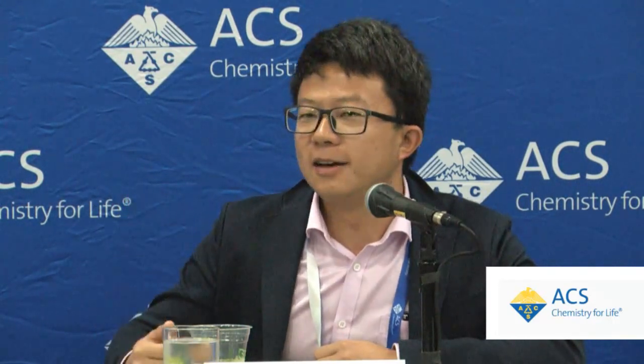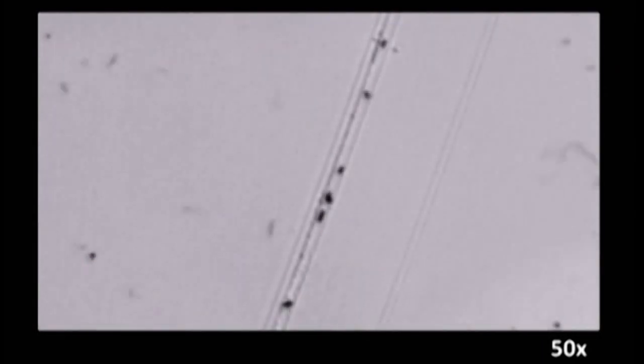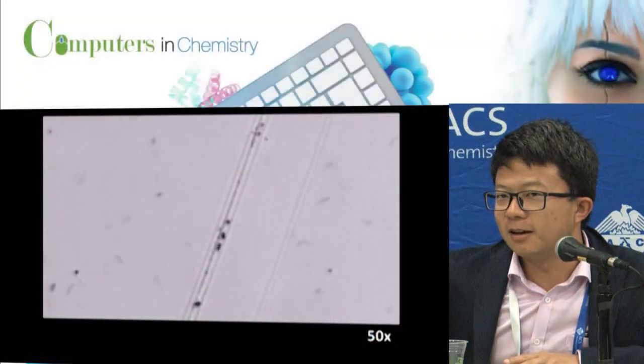How quickly does it repair? The video shown is five minutes, but we accelerated it — it actually takes about 10 minutes. Have you tested the crack after repair to see how strong it is? We tested how much the conductivity can be restored. Using a concentration of around 20 nanomotors per 100×100×100 micrometer volume — very dispersed particles — we showed that conductivity can be restored over 50 percent.